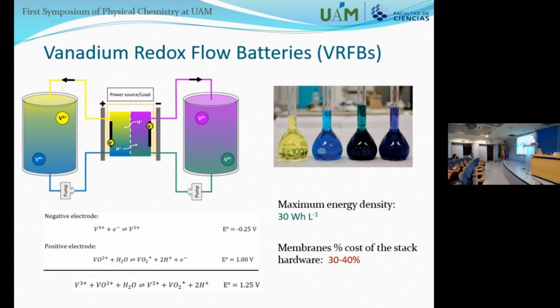What's very relevant is the membranes that are used to separate both chambers, because we have this process working in one chamber and the other process in the other chamber, and they have to be separated to avoid the mixing of the species. The membranes usually used nowadays account for approximately 30–40% of the final cost of the stack. So this is a really important drawback, and that's the main reason a lot of research is being performed to enhance the membranes and, of course, reduce the costs.